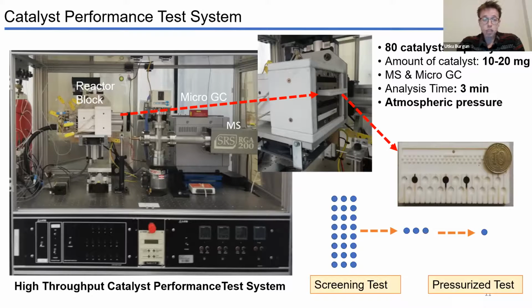The test system, which has a micro gas chromatograph and mass spectrometer, provides multiple and rapid scanning tests at atmospheric pressure. In the high-throughput test system, the promising catalysts are determined among the tested catalysts, and by analyzing only them in the pressurized test system, faster and target-based progress can be achieved.